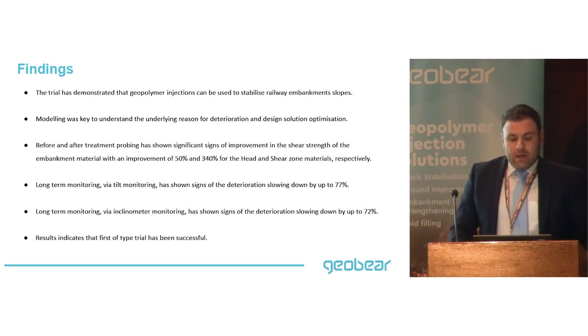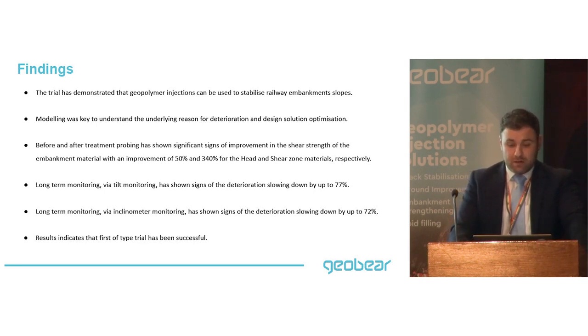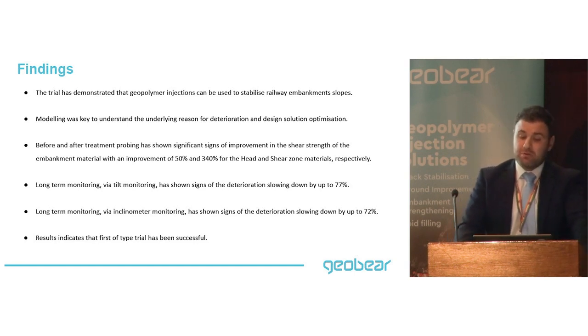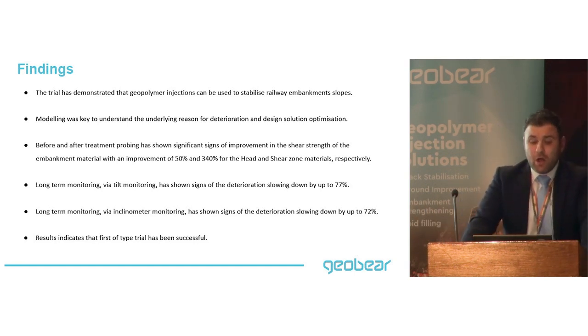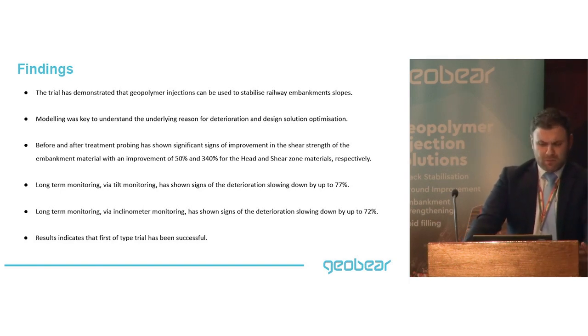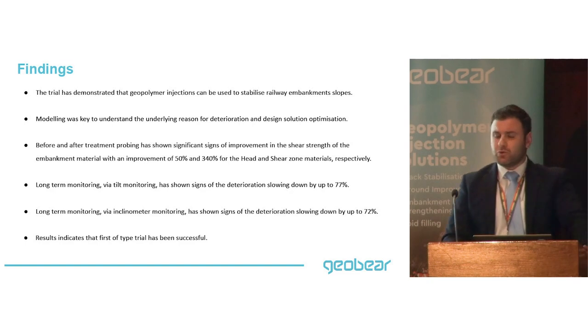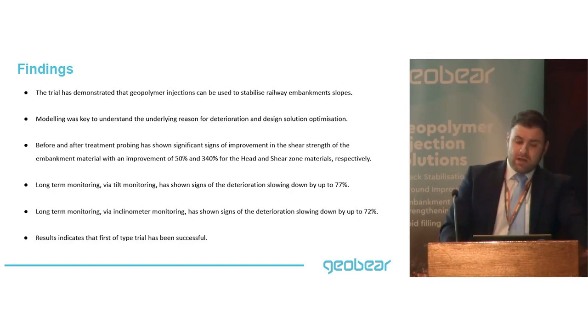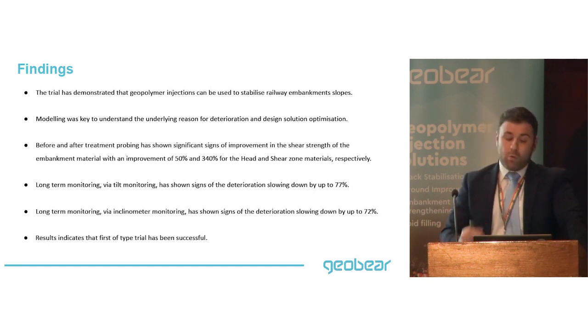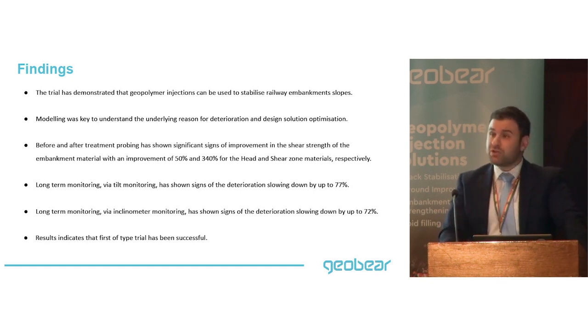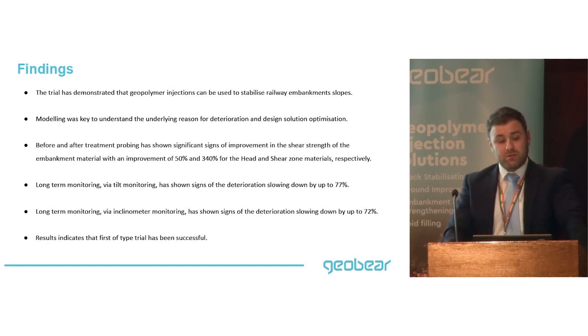Before and after probing has shown that we've managed to improve the shear strength of the weathered clay by about 50% and the shear zone by about 340%—we've seen that from the graphs. Long-term monitoring via the tilt sensors has shown we've slowed down the deterioration by about 77%, and we've seen similar values on the inclinometer monitoring data, where we showed a reduction in degradation of about 72%.